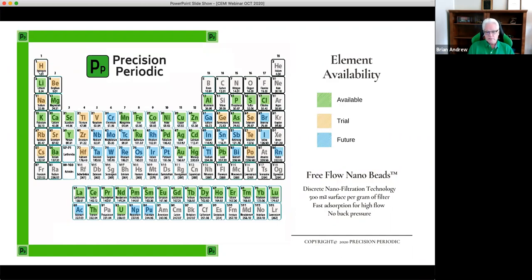And they have a fairly decent performance. For example, the gold filter will pull out 85 to 90% of gold in a single pass on one filter. And it does that in a couple of seconds, very fast kinetics. And the release is literally within a minute.